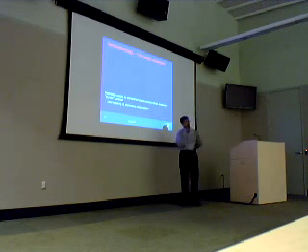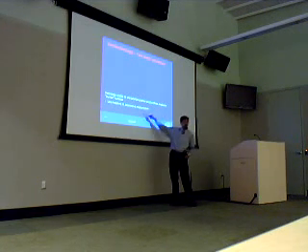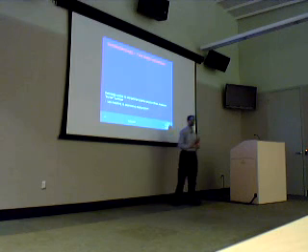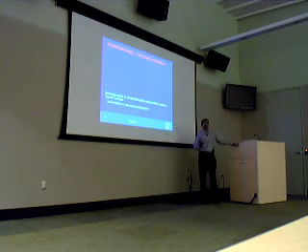The second paradox is metrology is unable to characterize these properties because they are so small and the measurement is for generally bulk materials and bigger structures. As a result, you use modeling to deconvolve measurement. So these two are why even if you are in smaller dimensions in nanotechnology, below 100 nanometers, you can't be predictive. Because you can't even measure, and even if you are predictive, then the point of validation is difficult.